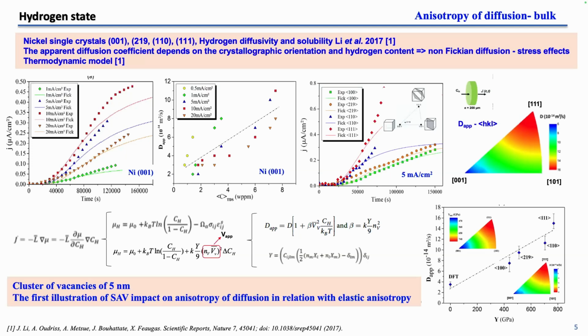And to model this effect, we use a thermodynamic process and implement the effect of elastic distortion induced by a defect on the chemical potential. And we show that, in fact, to describe that, we need a cluster of vacancies of 5 nanometers. By performing TEM, we checked that and we observed it. In fact, the anisotropy of diffusivity of hydrogen in nickel is induced by the production of vacancies during the ingress of hydrogen.